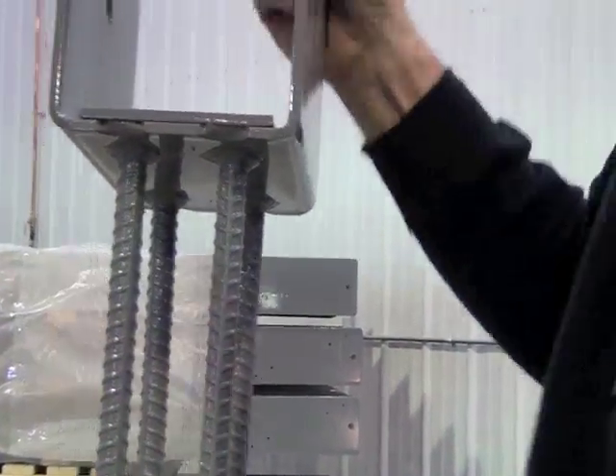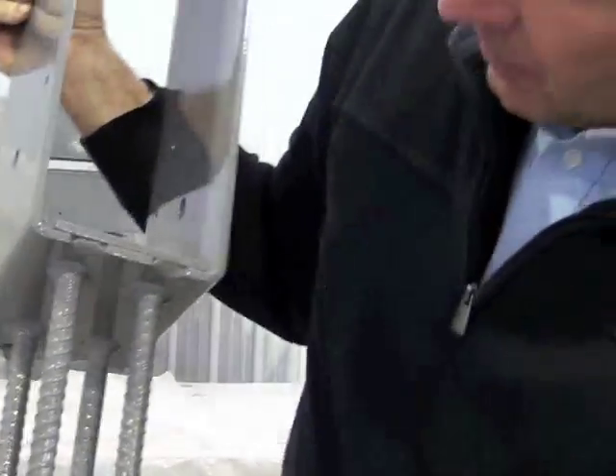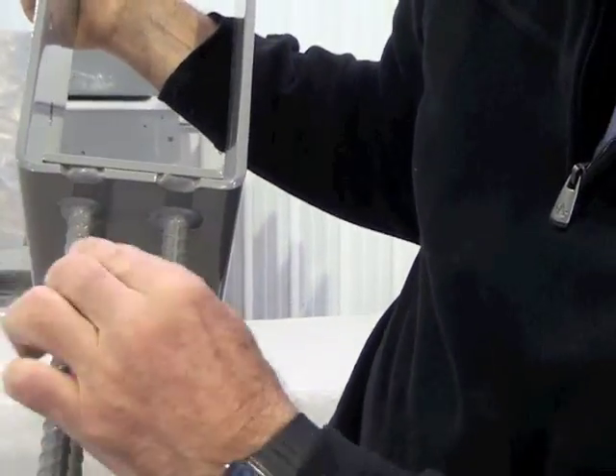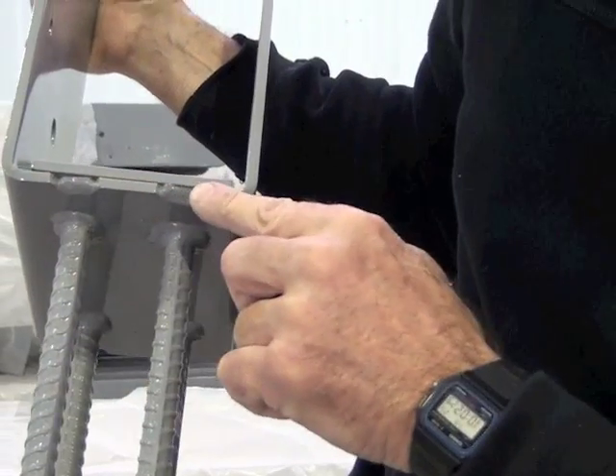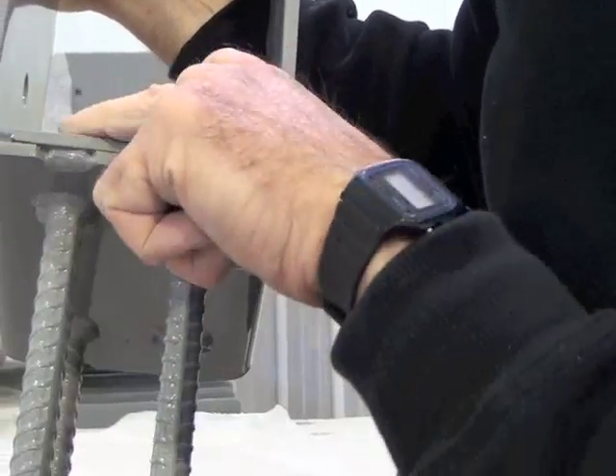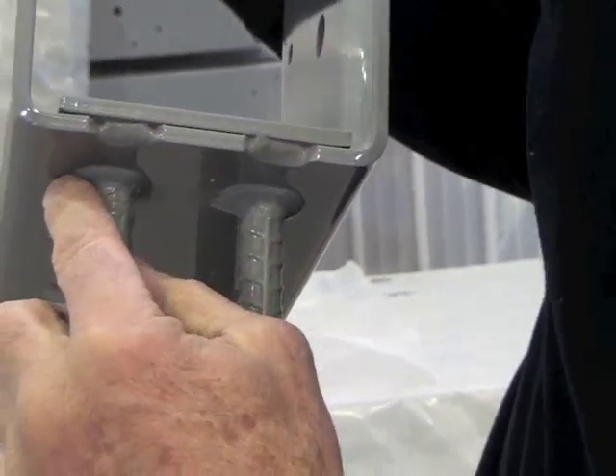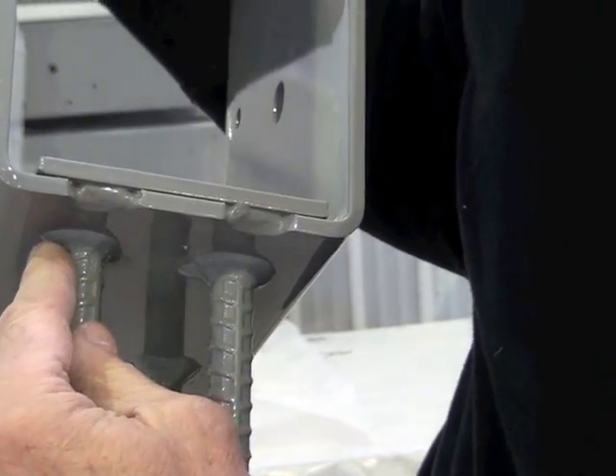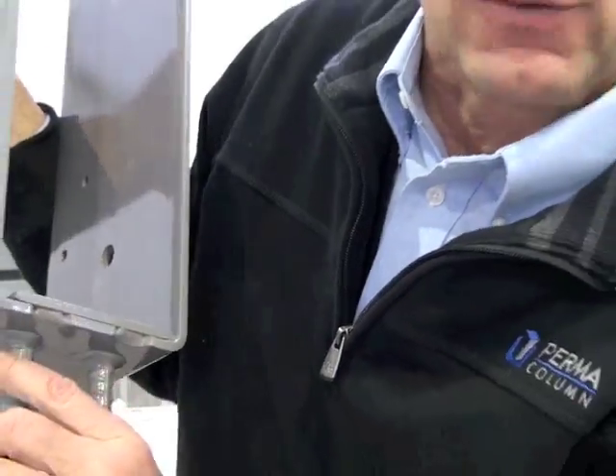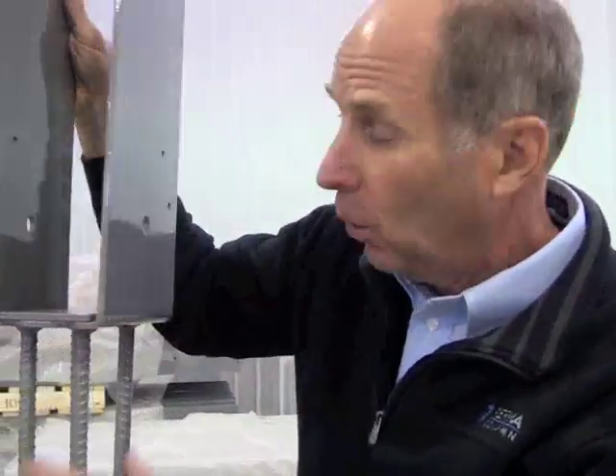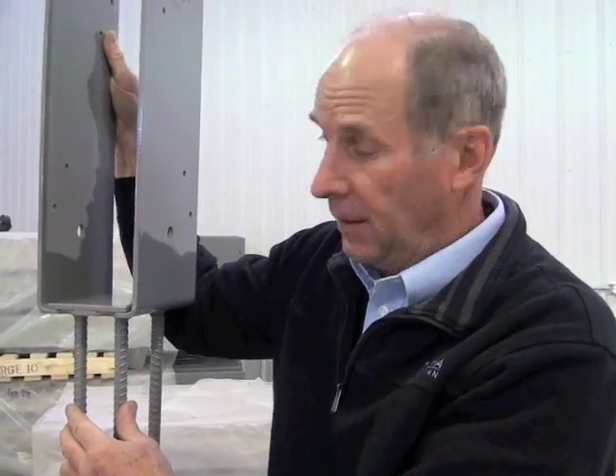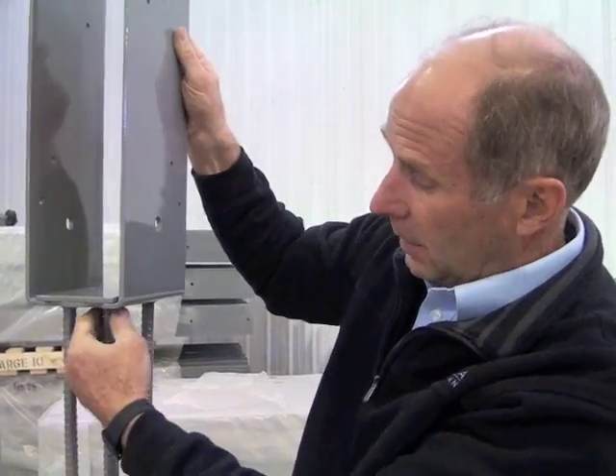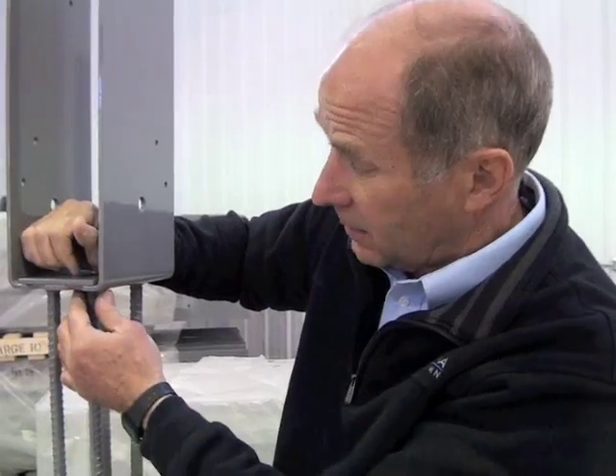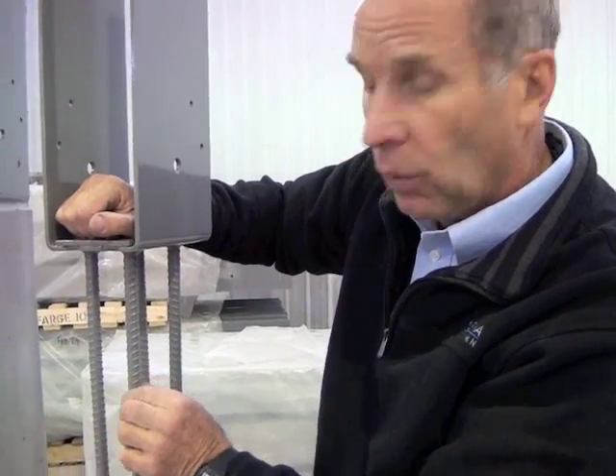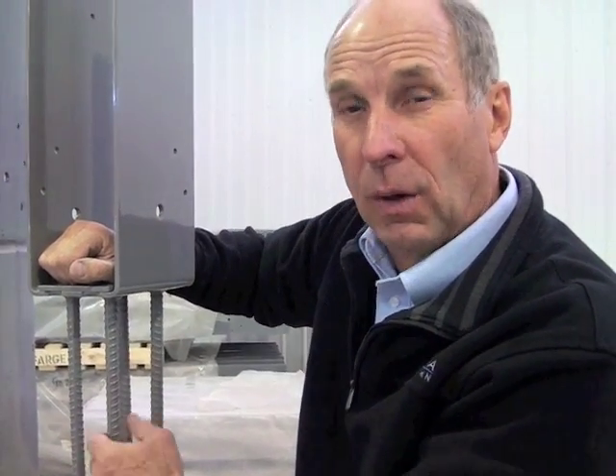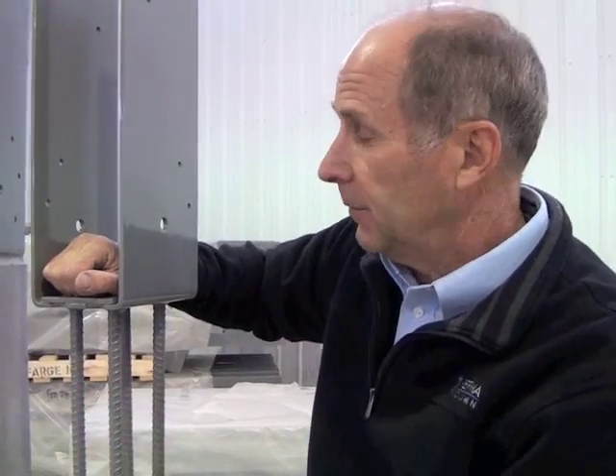And not only is this weld, if you can take a look at this, welded on here. It is actually, there's a hole punched in this bottom layer, and the rebar is inserted into that hole and butts up against this laminate. So this weld is not a butt weld, which is a much weaker weld. It's a fillet weld, and it gives us strength. As we're welding these in our factory, we do pull tests on every batch that we run, and we actually take a big hydraulic ram cylinder and pull against that and against the weld to see where we're at strength wise, and the rebar invariably tears here, so our weld is a lot stronger than the rebar itself.